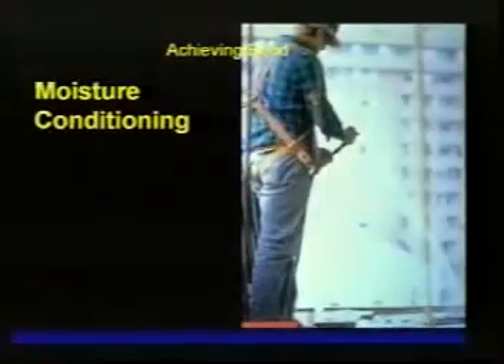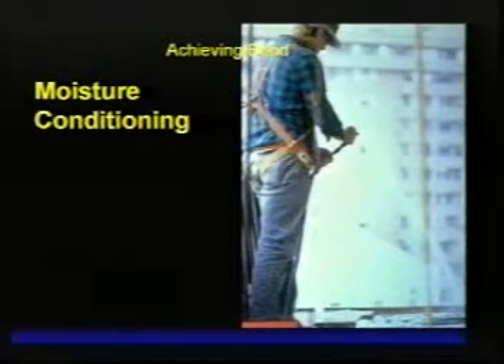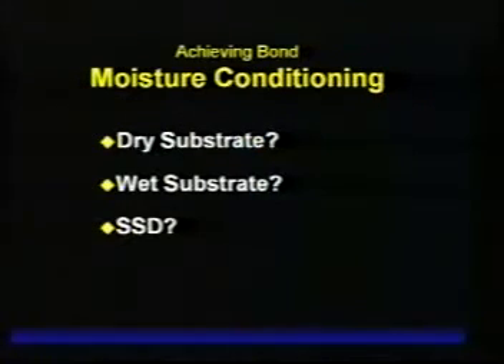So we have a pore structure in the existing concrete, and that's what this graphic is showing, is that we have a surface that will absorb the new repair material. And that kind of leads us into the moisture conditioning. All these three techniques, the question is, what is the moisture content that's required? And we have really three conditions: the dry substrate, a wet substrate, which is saturated, and a saturated surface dry substrate, which is kind of in between.